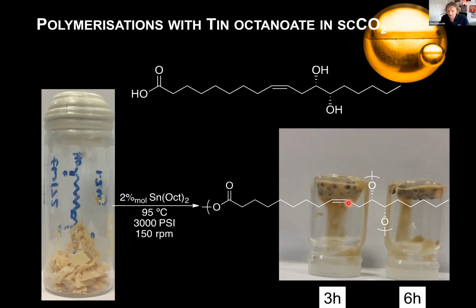The other thing we've done, which I didn't create a slide for here, is we showed that instead of using tin octanoate, we can actually use an enzyme, and we can do the polymerization at much lower temperatures using an enzyme and create very similar polymers. And the enzyme, a natural catalyst, survives in CO2.